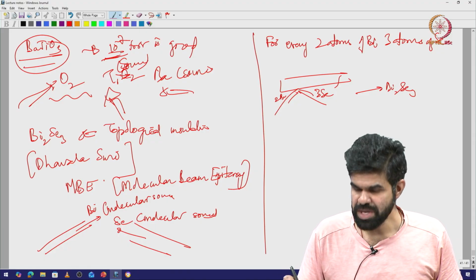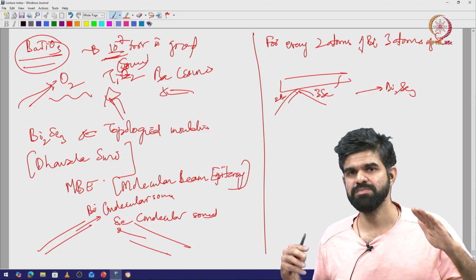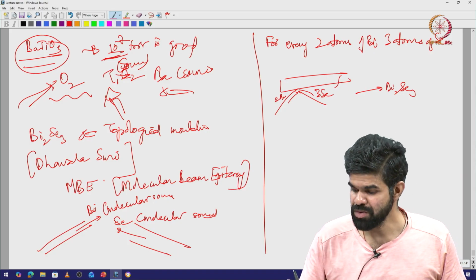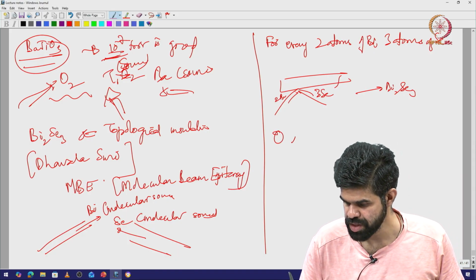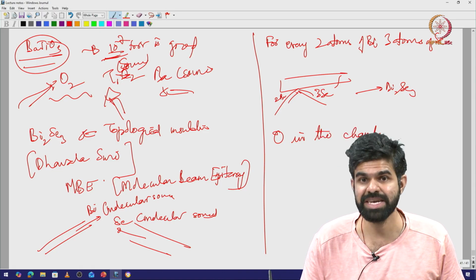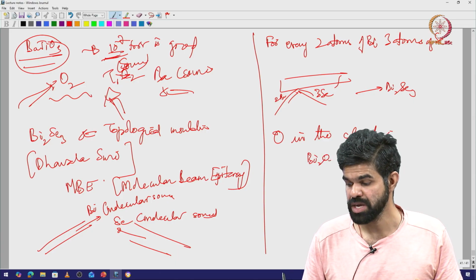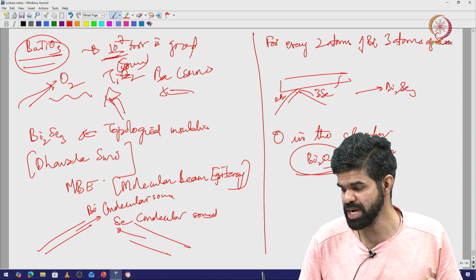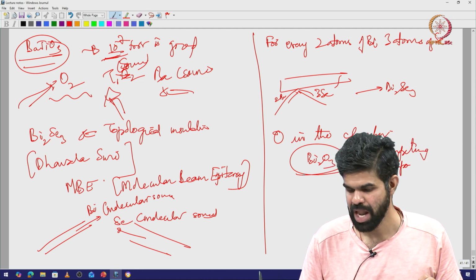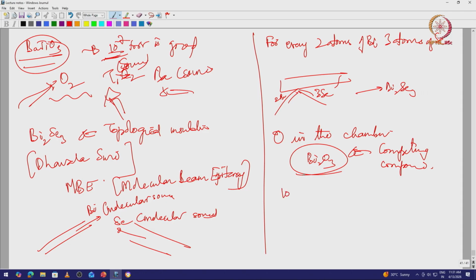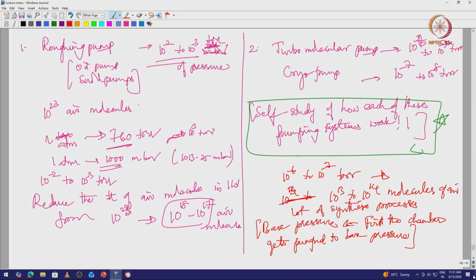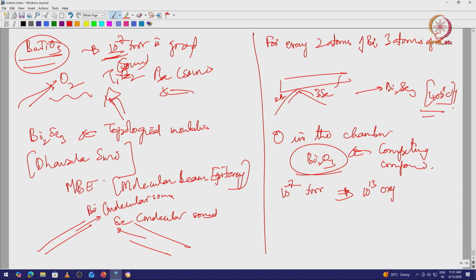Now the question to you is, I want for every 2 atoms of bismuth 3 atoms of selenium, but it turns out that if I have oxygen in the chamber, the other competing compound is something like Bi2O3. This is the competing compound which I do not want to grow, especially when my pressure is 10 power minus 7 torr, let us say, and I am doing this reaction at some 400 degrees Celsius. I do not know where she does the reaction, I can check with her. At 10 power minus 7 torr, we said how many oxygen atoms are there? There are about 10 power 13 or 10 power 14 oxygen.